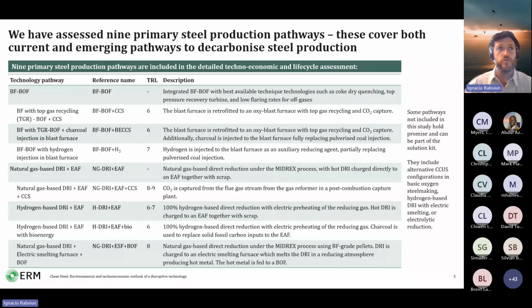In terms of the direct reduction routes, other than the unabated and conventional natural gas-based pathway, we looked at CCS, where CO2 from the flue gas stream from the gas reformer from the direct reduction plant is captured. And then we looked at 2 hydrogen pathways. Both pathways represented a 100% hydrogen-based direct reduction. That is, there are many combinations of hydrogen and natural gas plants that are being proposed and studied, and many incumbents are planning to build gas-based direct reduction facilities with a gradual transition to hydrogen. In this case, we modeled 100% hydrogen use.